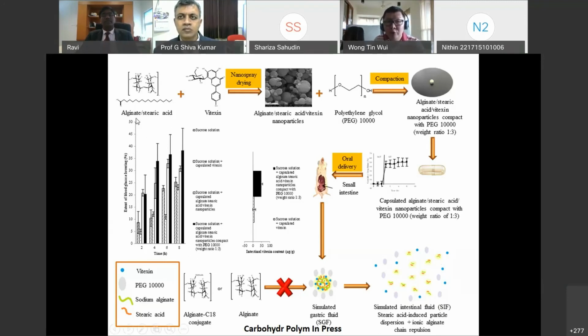We have the alginate and stearic acid mixture, and we mix it with vitexin. We spray dry it into nanoparticles, and subsequently we compact the nanoparticles with polyethylene glycol 10,000 into the form of a compact, right? This is a very small compact and is inserted into the capsule and administered in vivo for oral anti-diabetic action.